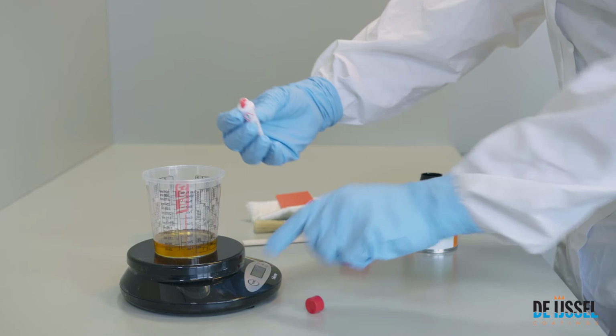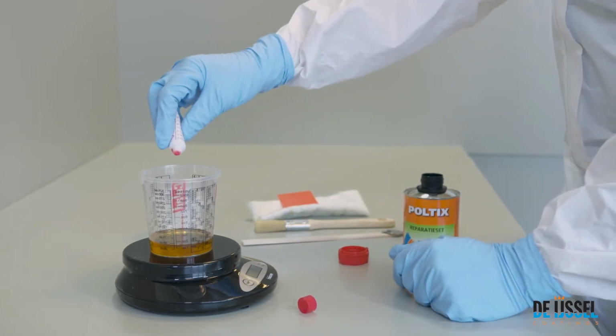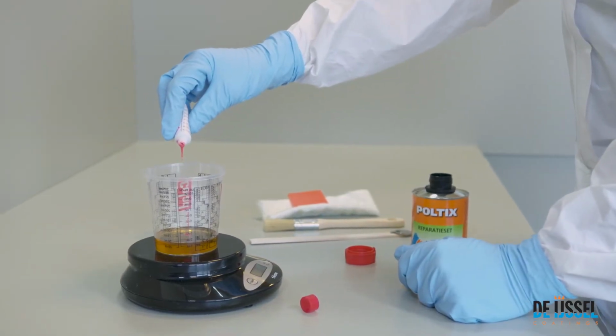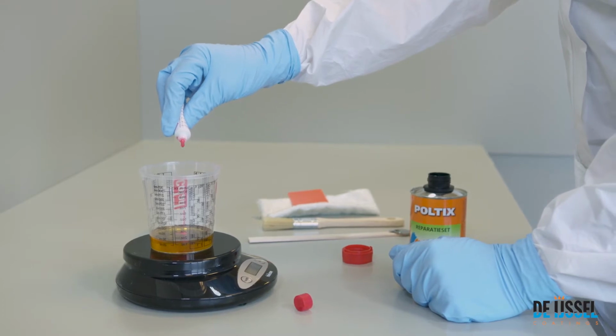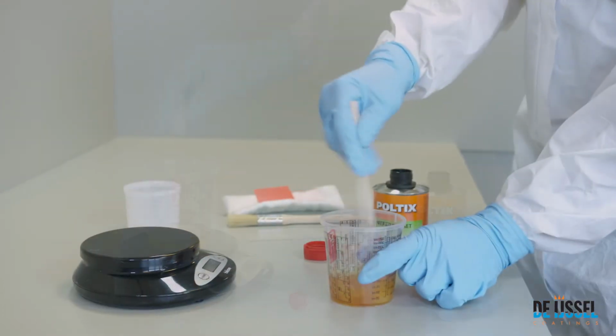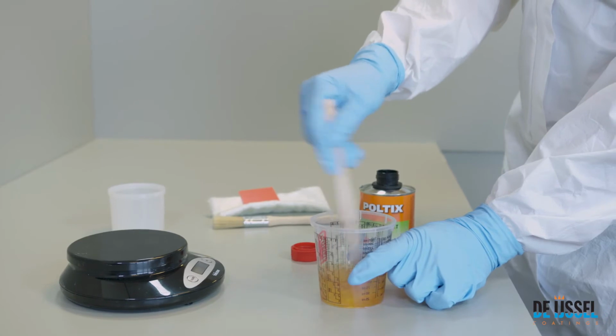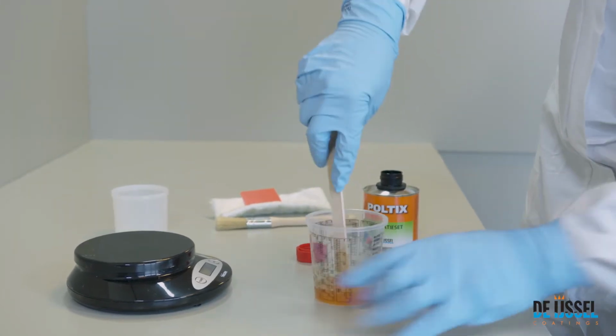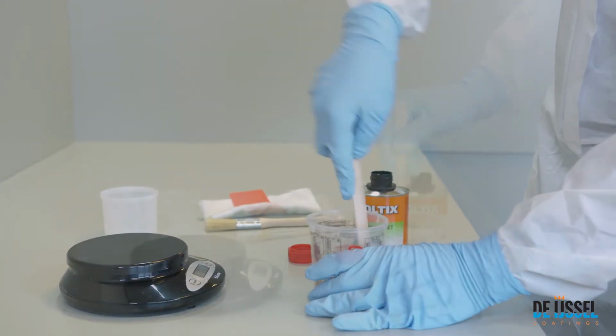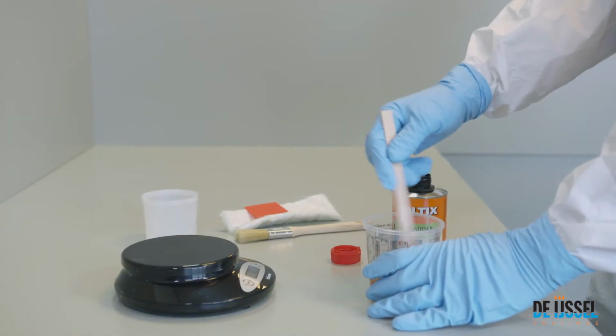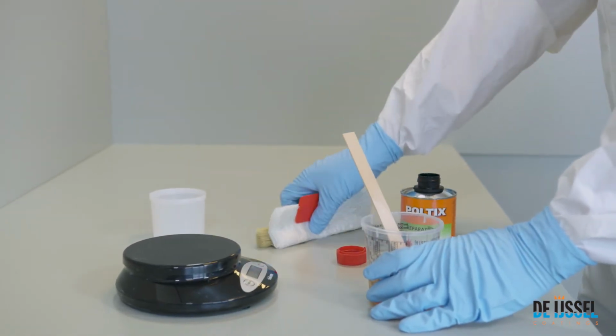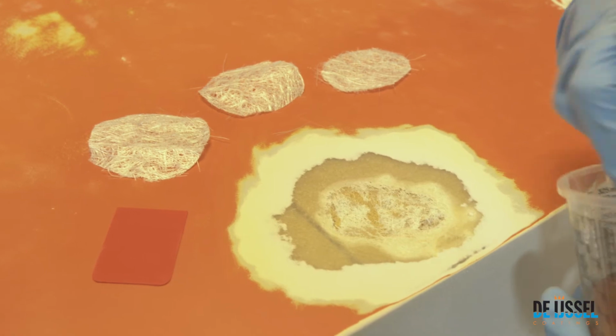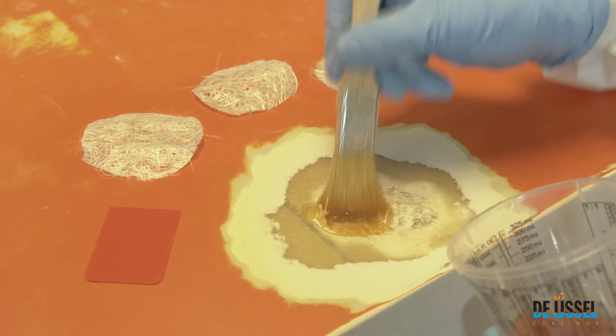Add the hardener in the right proportions, 100 parts by weight base and 2 parts by weight hardener. Mix the components thoroughly before use. Only mix as much as can be applied within the processing time. For each layer, the fiberglass cutout should be slightly larger.